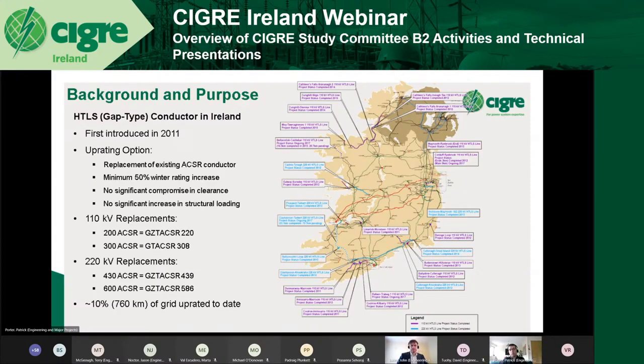In total, we had 4 designs of the gap type HTLS used here in Ireland, 2 at 110 kV and 2 at 220 kV. And I think to date, approximately 10% or around 760 kilometers of the transmission grid has been upgraded, but I would say that figure is likely to be closer to 850, possibly, with work ongoing in the next 12 to 24 months.